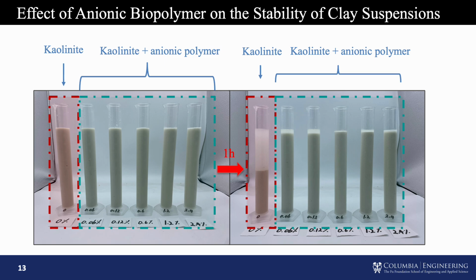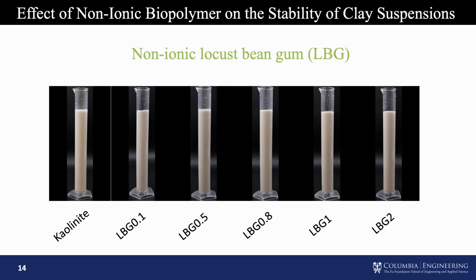you can see we added 0.06%, 0.12%, 0.6%. So basically 0.12% is enough to get a pretty stable suspension. And these two suspensions have very different flocculation or settling behavior. On the other hand, the binding polymer, the non-ionic locust bean gum, can accelerate the flocculation process. We can see from the video, compared to the pure kaolinite control, the locust bean gum addition significantly accelerates the flocculation process. This is because you can imagine if a polymer binds to one clay particle, it can also bind to another clay particle. This kind of bridging effect can accelerate the flocculation of the clay. Eventually, it will accelerate the settling behavior.